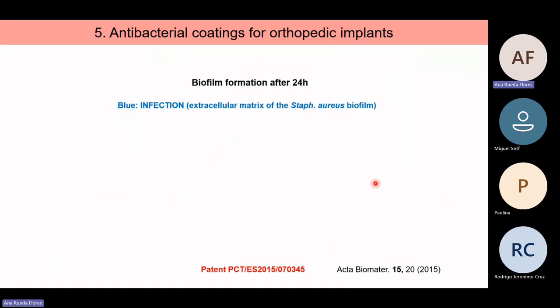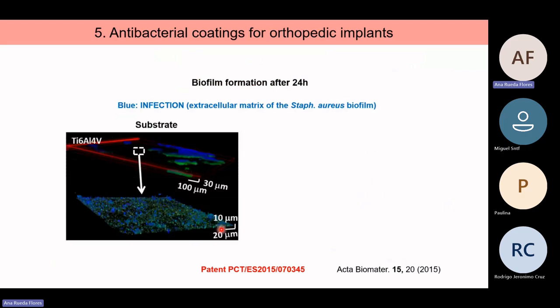So we are culturing bacteria on purpose, in this case Staphylococcus aureus, for 1 day. And we are going to stain in blue the extracellular matrix of the bacterial biofilm. So on the initial implant without the coating, this is what we have after 1 day. Big blue islands, so big infection in this region. But even in those ones, when we zoom in, you can see blue dots everywhere. Green dots are alive bacteria, blue dots, bacteria that have produced the bacterial biofilm. So infection is developing everywhere.